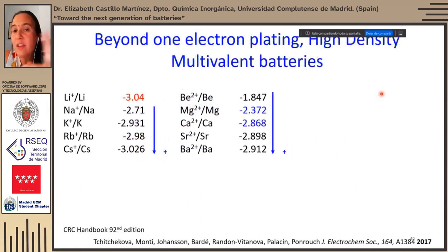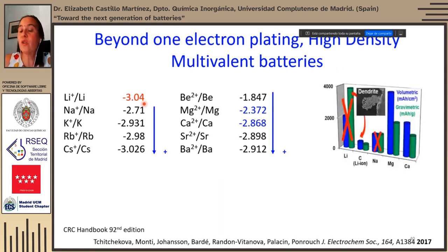So what is beyond lithium, beyond sodium and potassium ion? We have the multivalent chemistries. We've seen already they are all very abundant, and magnesium and calcium, specifically calcium, has a voltage of reaction which are very close to those of sodium and potassium. However, both of these chemistries, I mean, magnesium intercalation was investigated earlier, but calcium ion batteries has started to be explored more recently, and they do not have larger specific capacities, but actually because they can exchange 2 electrons or 3 in the case of aluminum, the volumetric energy densities are even higher than that of lithium-ion batteries.